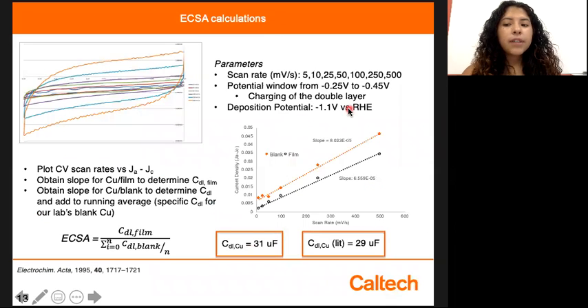In order to calculate the ECSA, we took values at 7 different scan rates and used a potential window from negative 0.25 volts to negative 0.45 volts, which is just enough voltage to charge the double layer capacitance without having too many side reactions happening. And we deposited the film at negative 1.1 volts versus RHE.